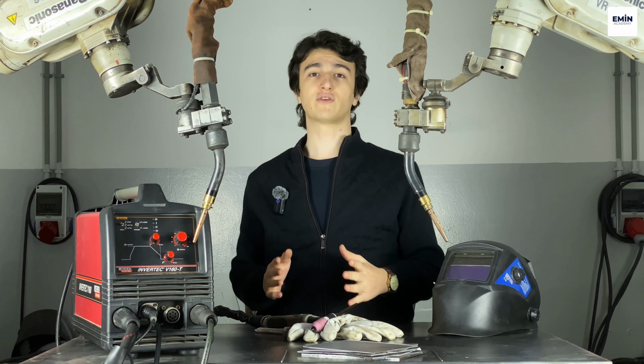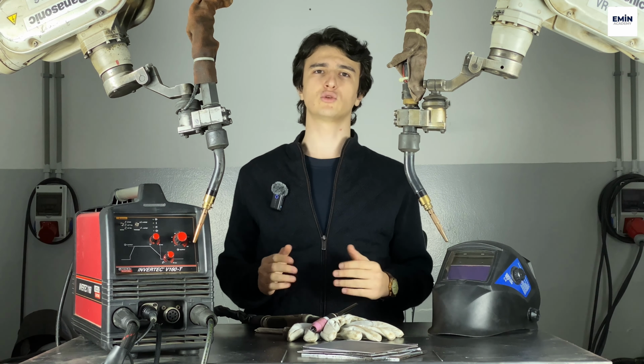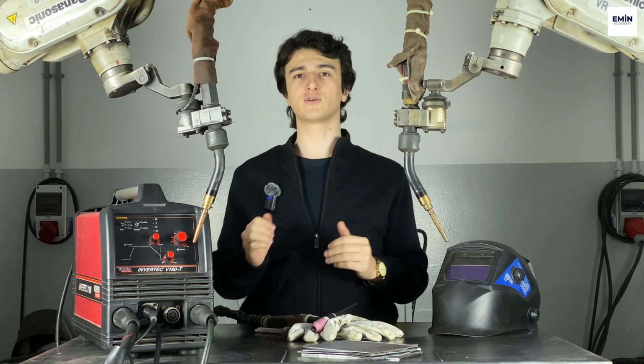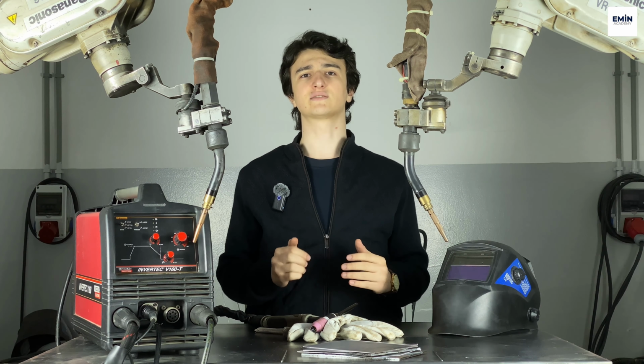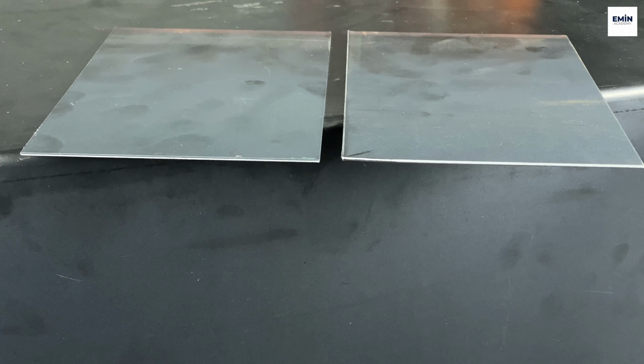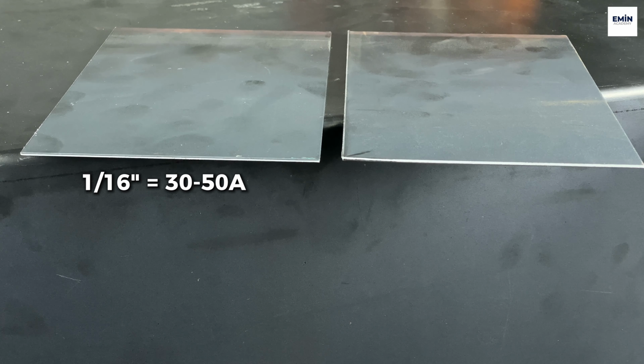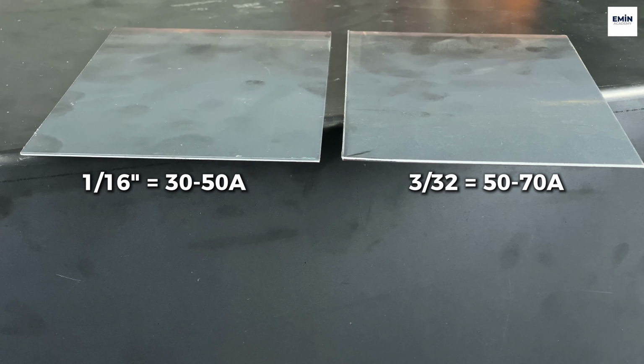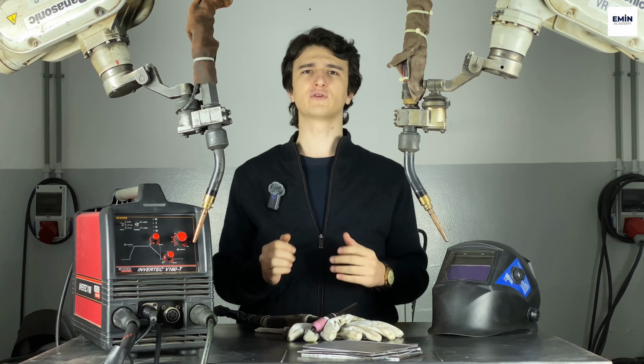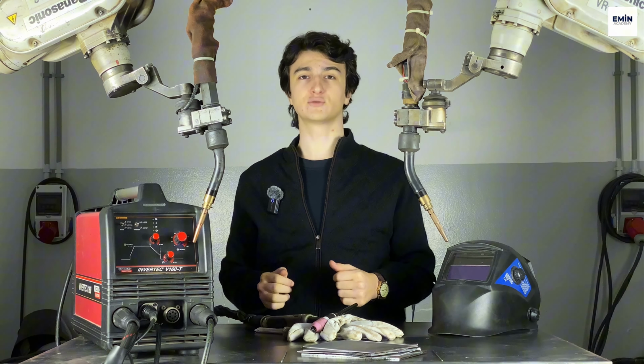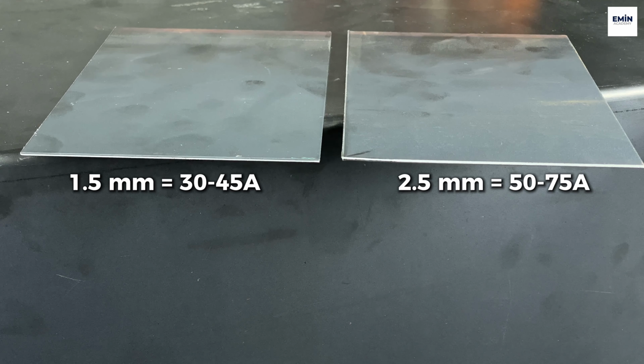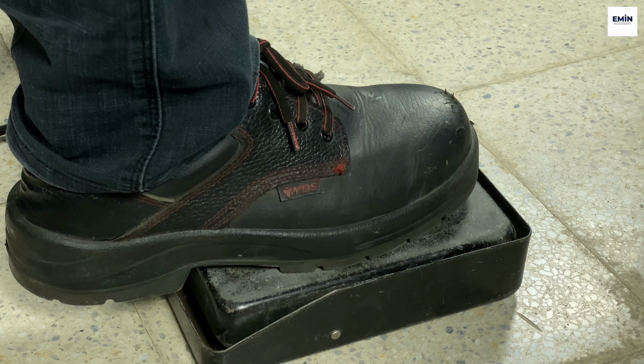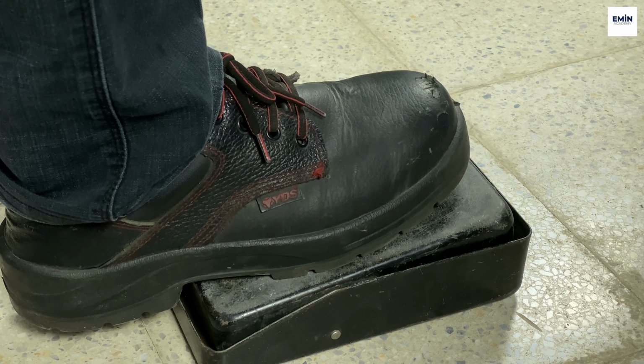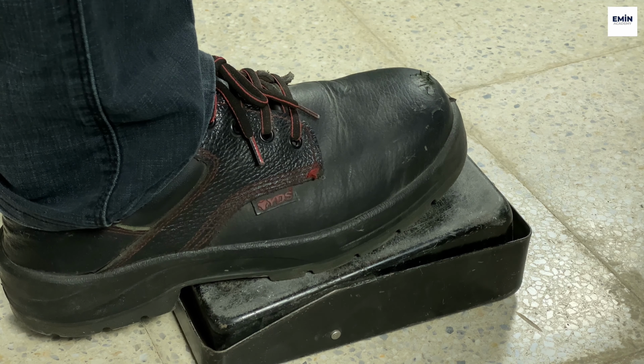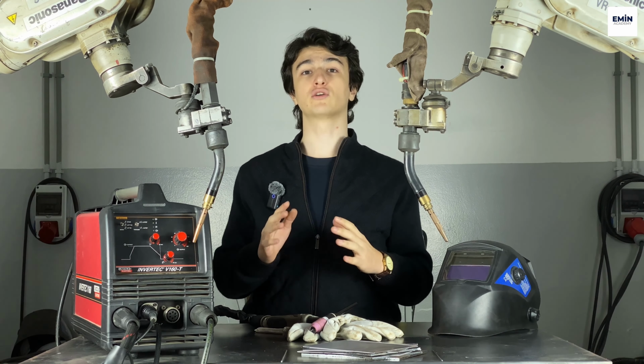As a general rule for thin carbon steel TIG welding, use about 20 to 30 amps for every 1/32 of an inch of thickness. For example, 30 to 50 amps for 1/16 inch carbon steel and 50 to 70 amps for 3/32 inch is suitable. For those using the metric system, the equivalent rule is roughly 20 to 30 amps for every millimeter of material thickness. Once the weld pool forms, gradually reduce the amperage with the foot pedal as you move to keep the heat under control. This minimizes the risk of burn through and warping.